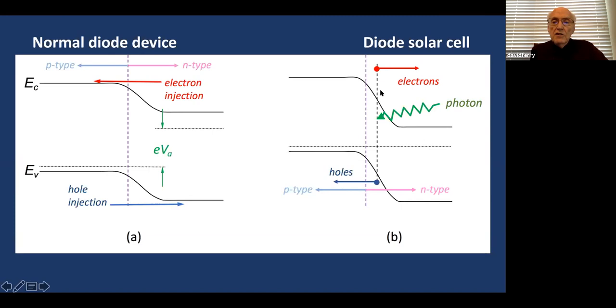Now, silicon cells need this area out here to absorb photons, and you need the ambipolar diffusion because the absorption coefficient in silicon is weak. If you have a III-V cell, where the absorption coefficient is large because of the direct gap, you can make the whole solar cell just the depletion region with proper design. And so you can get a lot better behavior that way. So those are some of the differences.